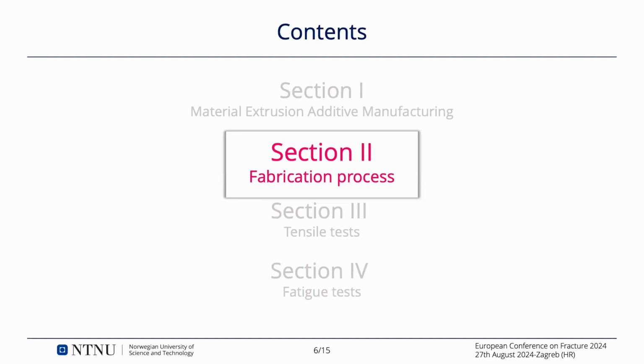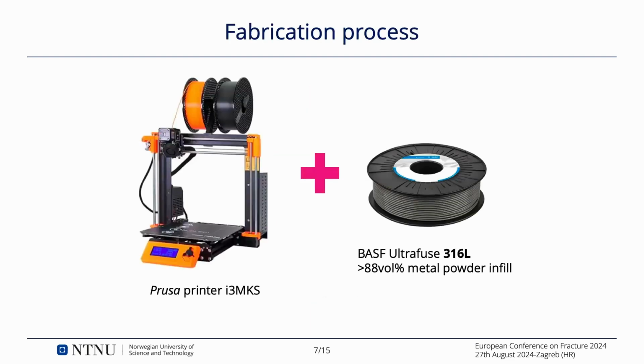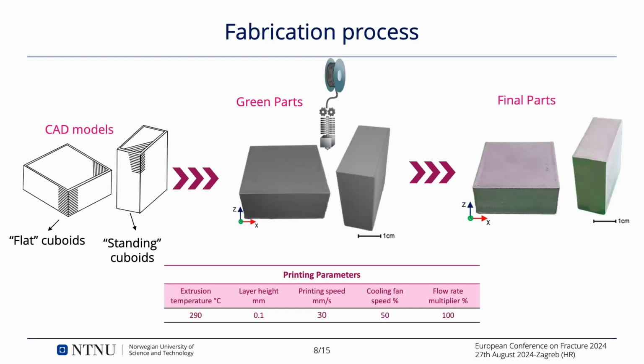So what we did, we used one of those printers and a filament that contains 316L metal powder. And for these experimental campaigns, we wanted to produce these cuboids, so very simple shapes. You can see the CAD models, the green part in the middle and the final parts, and we printed them in two orientations, flat and standing on the printing platform. The tuning process of the printer was actually quite demanding. So here I've listed just the main printing parameters, but there are many more that one can change.